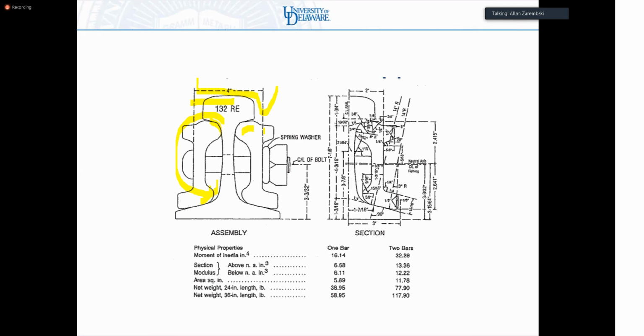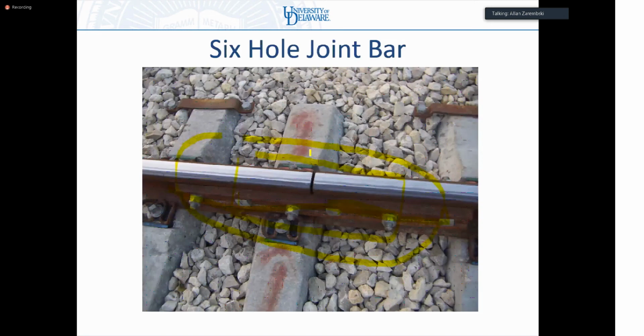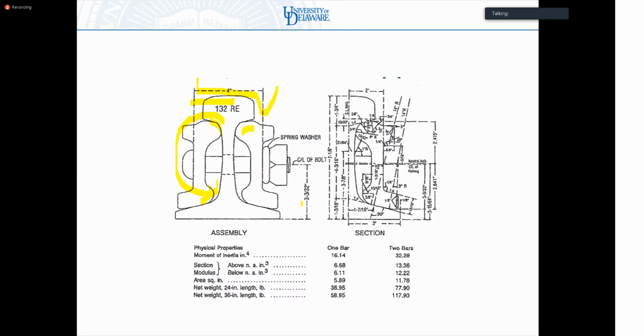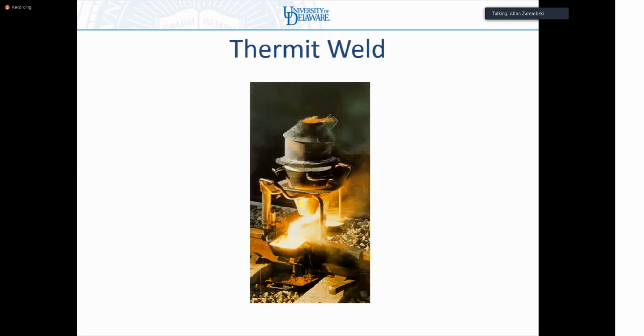The design of the joint bar is generally so that the moment of inertia of the two joint bars is equal to the rail section, so that in this one gap area, the joint bars have sufficient bending strength to match a rail section and they don't overstress the rail. Of course, in this zone, you have a higher moment of inertia and you have less bending and lower stresses. But in this gap between the two rails where the joint bar is, you want the stresses to be no different than what you see in normal rail. So that's a joint bar.